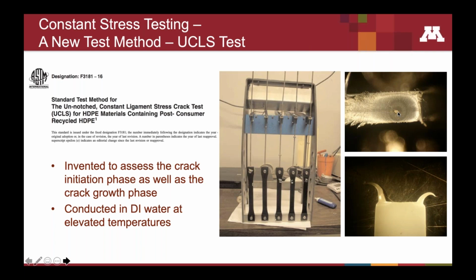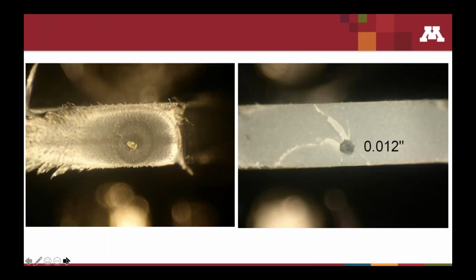Some contaminant caused this specimen to crack, and then the crack propagated right or left of that specimen, and eventually we saw ductile tearing on the end of the specimens. So the idea was to say, let's invent this new test method, and then let's try to relate that time to cracking to the service life of the product.